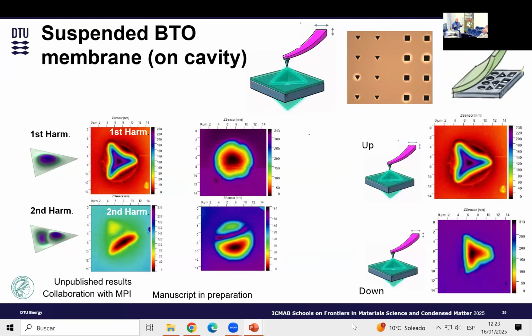What we are currently also doing, we're using a PFM and trying to actuate the material, trying to find the resonance of each cavity, depending on the size and the shape of the material. And it's not trivial because these holes couple to each other. So when you resonate one of them, you get some effect from the others. We didn't talk about it, but we saw that when we actuate one, we get different resonances. And we figured out now how to isolate the membranes and look at a single one at a time.